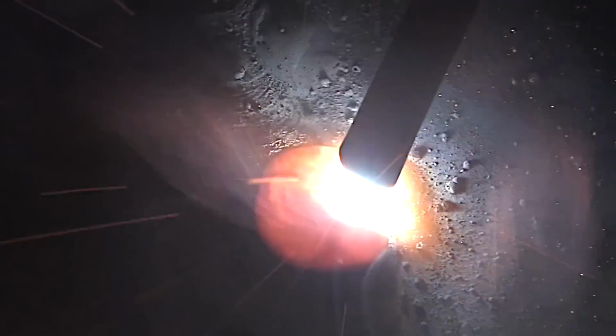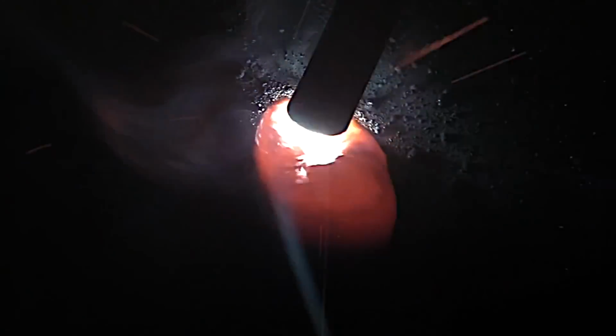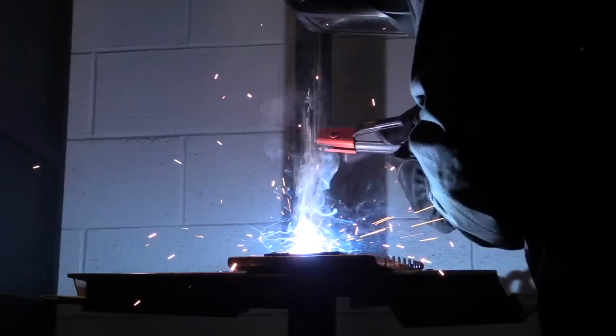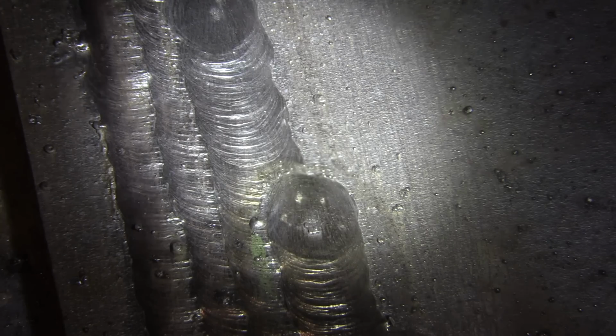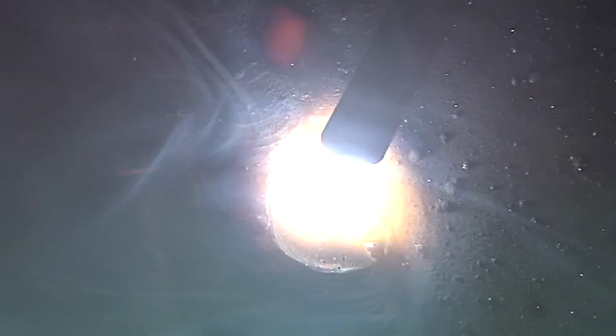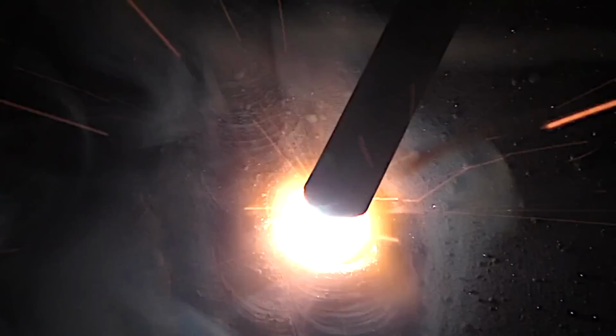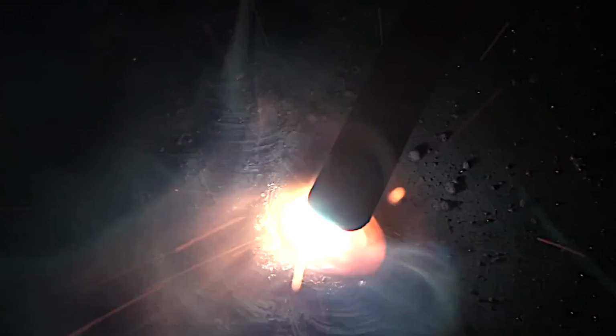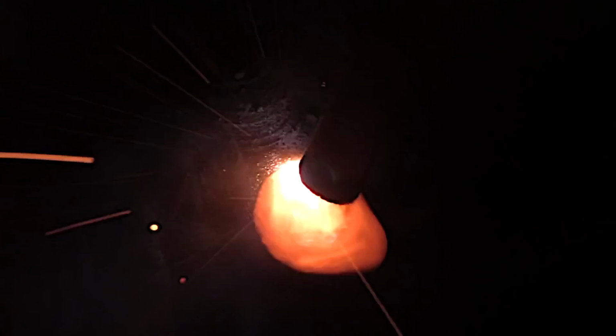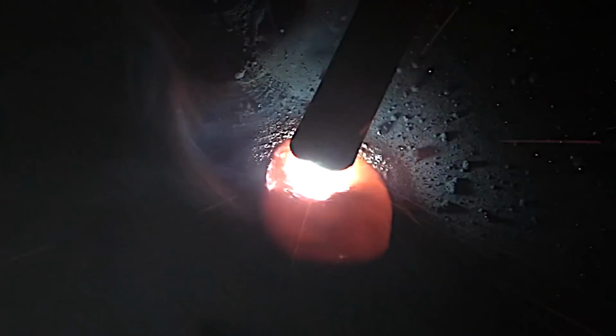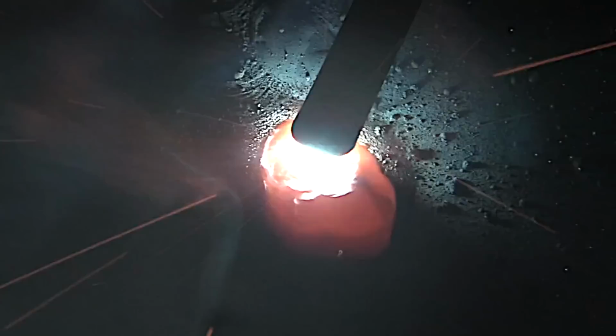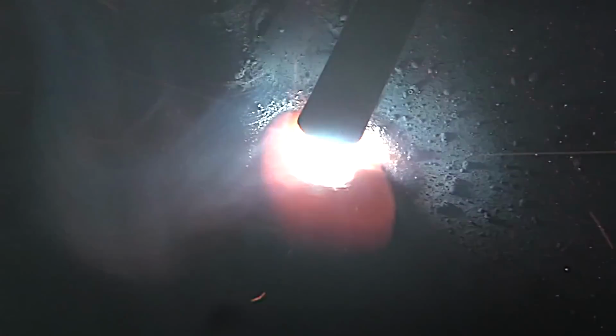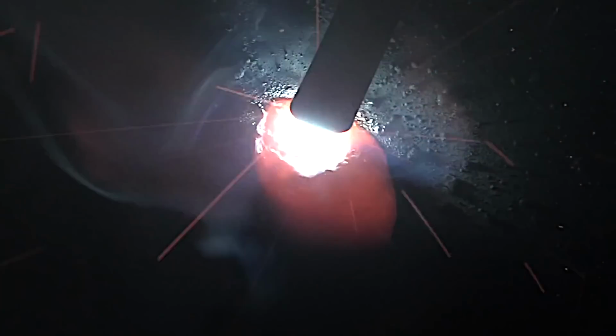You want to light up just ahead of the crater, long arc a little bit, go right into the crater, and carry on. This all happens very quickly, so I'm going to show this in slow motion, in quarter speed, lighting up about a half inch or so ahead of the crater, aiming for the center of that crater, letting that crater fill, and then carrying on. Again, this happens so quickly, and it really warrants a lot of practice. So if you want to get good at restarts, weld about 2 inches at a time, chip slag, and restart, and you'll get good at restarts.